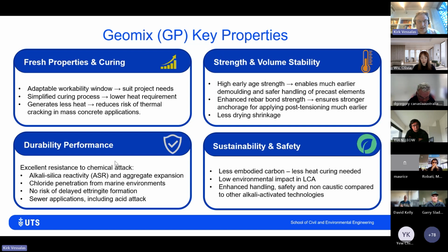In terms of durability performance, we've done some work on ASR, alkali silica reactivity, and aggregate expansion. We're finding that the geopolymer product is performing on par with fly ash blends and also slag blends, both binary and ternary, for mitigating ASR. There is exceptional resistance to chloride penetration, a little bit better than conventional ordinary Portland cement systems. One real key thing going for this technology is there's no delayed ettringite formation because there's no sulfate balance or sulfate depletion required, as in ordinary Portland cement hydration. And very, very good resistance to acid attack, particularly for sewer applications.